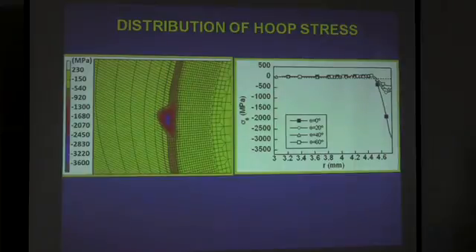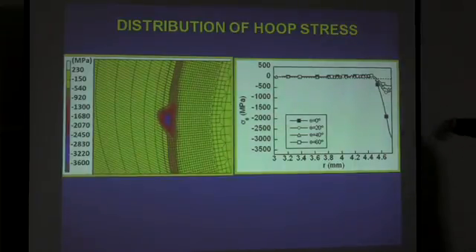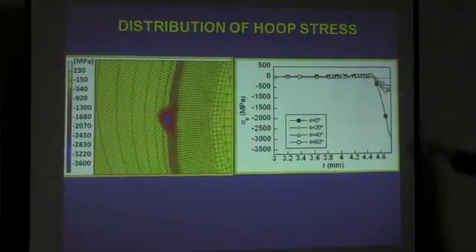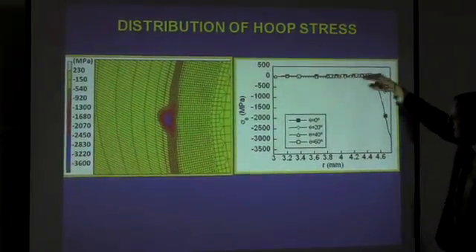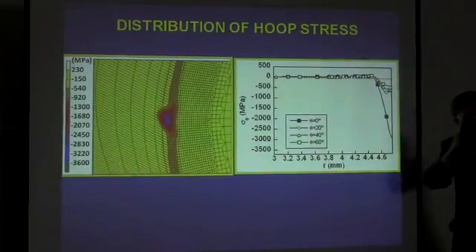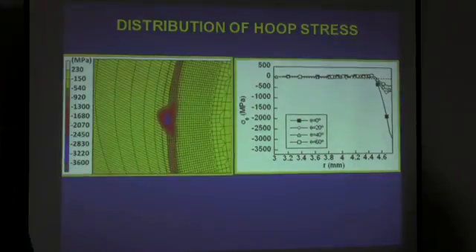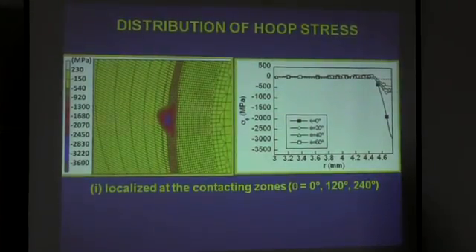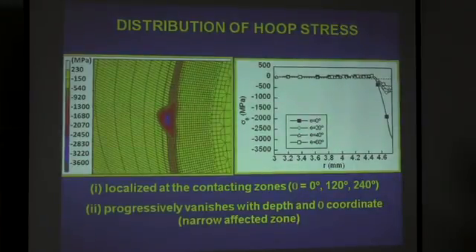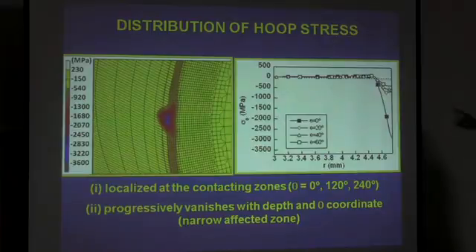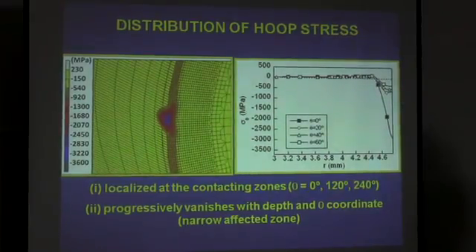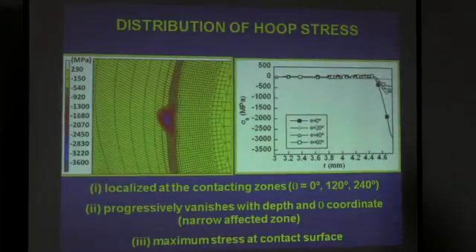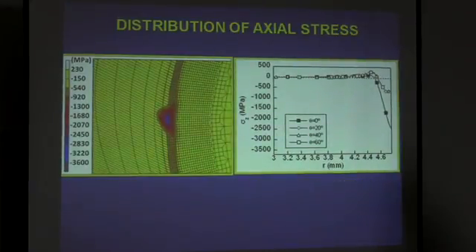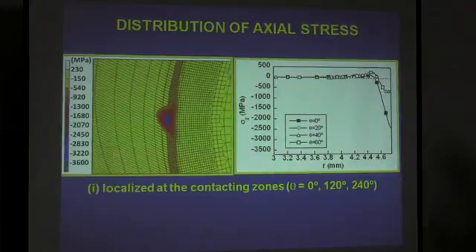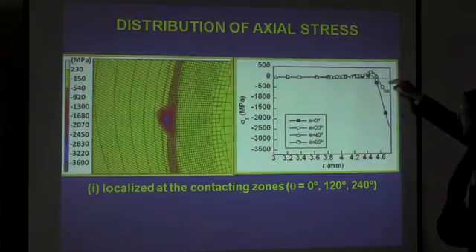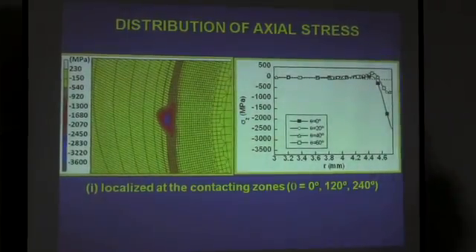With regard to hoop stress, similar distribution. The hoop stress, again concentration and compressive in the contact area, relaxed in deeper points, and also relaxes when the angle increases from the contact plane. Localized at the contacting zone, 0, 120, 240, progressively vanishes with depth and θ coordinate, narrow affected zone. This is the zone of compressions, a strong compression due to the rolling contact fatigue, and maximum stress at contact surface. Negative stress. With regard to axial stress, similar distribution, again contacting zones have the maximum distribution, and it vanishes with the increase of the angle.